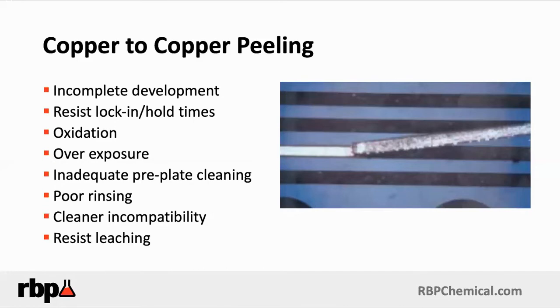There are other issues with adhesion failure to consider. There could be debris on the surface from inadequate rinsing, or we didn't do a good job of developing the photoresist in the pattern plating process. If we left residues that we can't see, that's going to act as a barrier and cause the electrolytic copper to peel. When troubleshooting this defect, look at any interruptions in the current. Did we micro-roughen or clean the surface prior to plating? Look at rinsing — good quality deionized water is very important. But avoid long rinse times that can lead to oxidation, which then causes peelers.